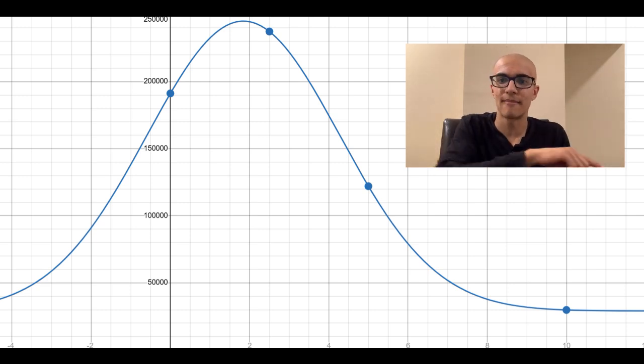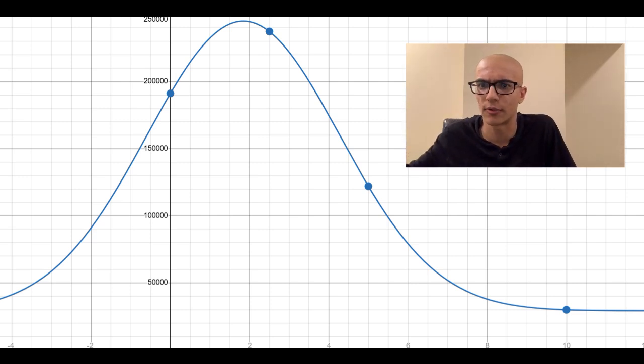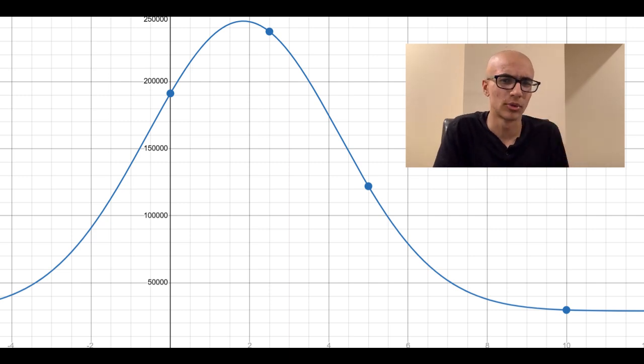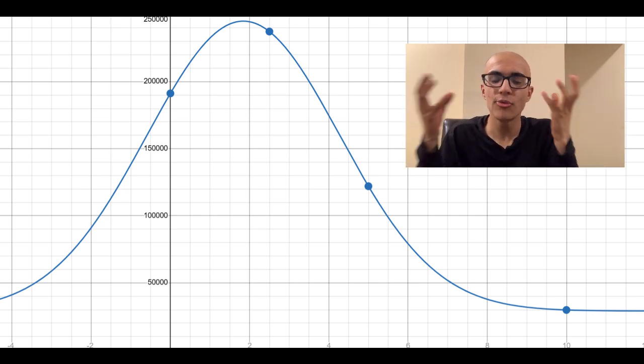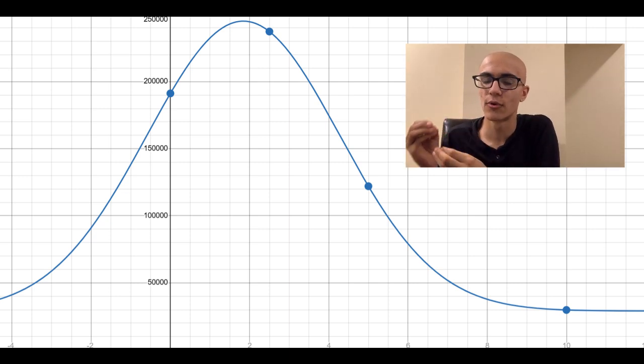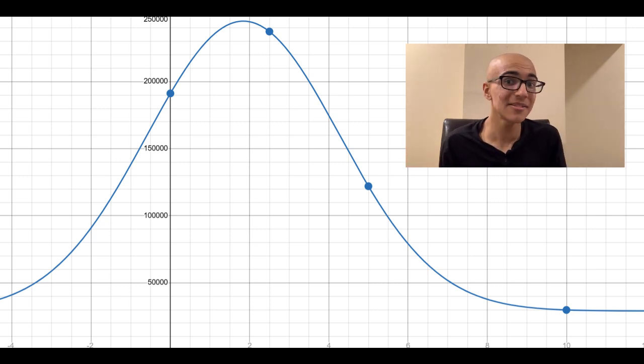Now, there's also some kind of maximum value. It kind of curves up like this. You can see it on the graph. So I chose the normal distribution as a possible curve to fit to this. That may not be the only curve, and I'm going to explore this over the next couple days. But right now what it's predicting is that there's a maximum value at around 2% clay concrete, rather. In other words, when you add 2% clay and 98% concrete, you get a mixture that's actually stronger than the regular concrete that's in our buildings. That, to me, is super, super, super cool. That we can actually, using modified clay, make a concrete that would be viable in our world right now.